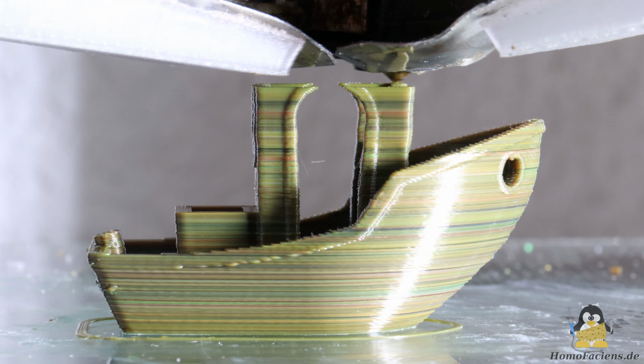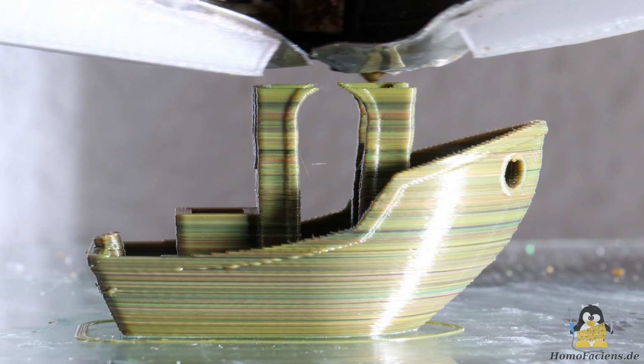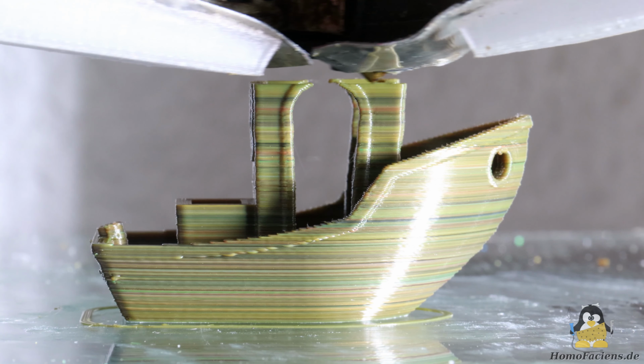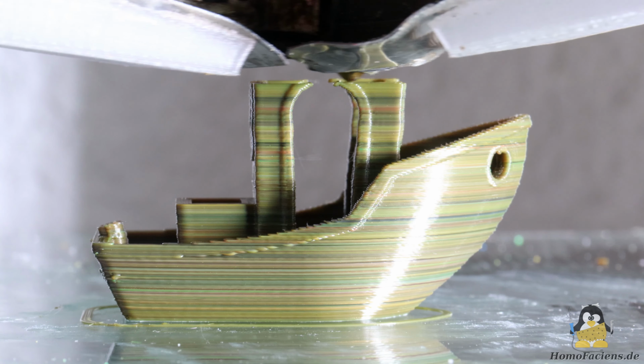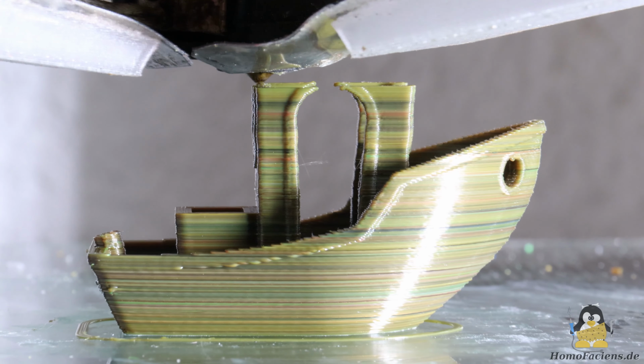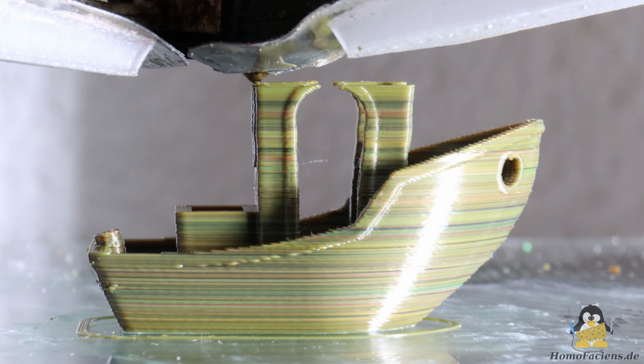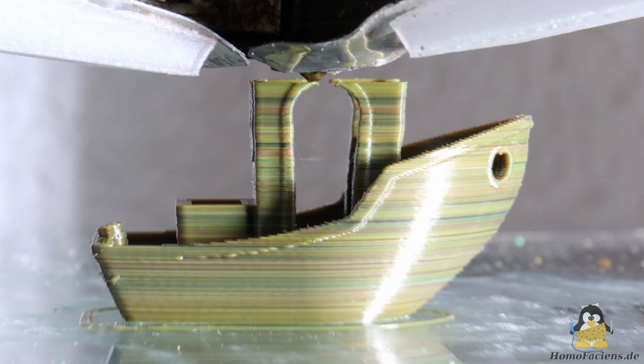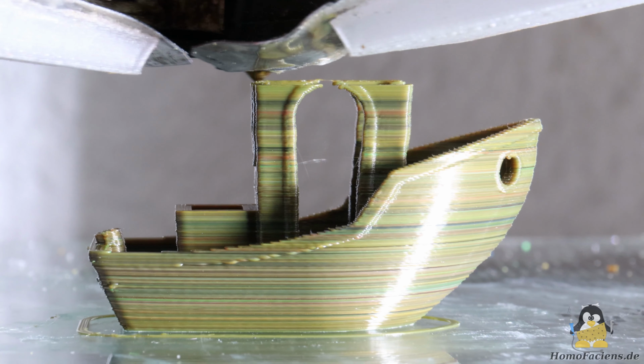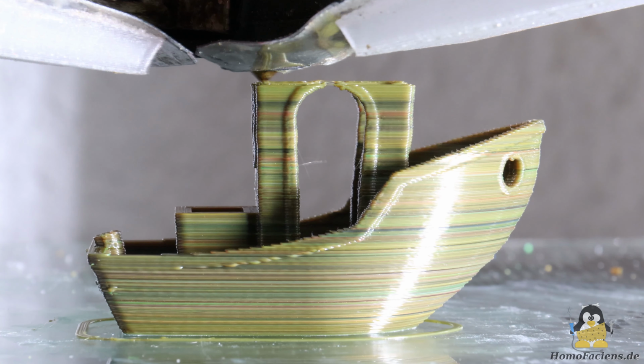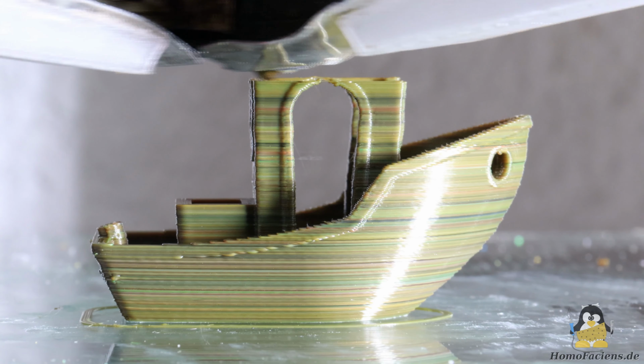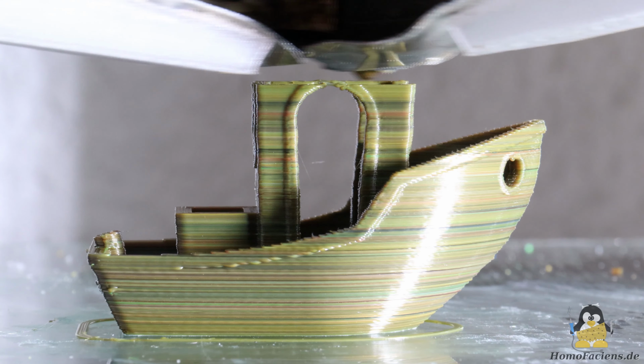When transitioning from the window openings to the roof, the printer resumes printing with high speed after a long, slow speed period. However, it takes time for the necessary pressure to build up in the extruder tube. As a result, under-extrusion occurs, which manifests as gaps on the outer wall.